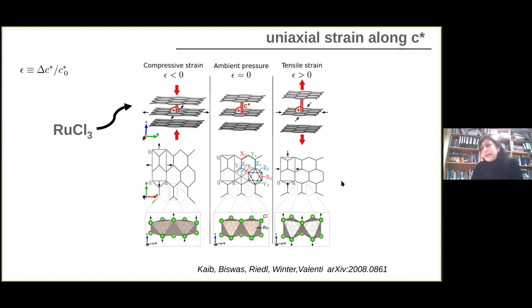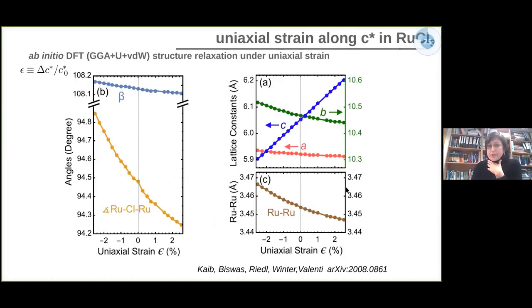So you can very nicely see these different cases by doing ab initio calculations, and you can see precisely what I was describing to you now in terms of these graphics, where I show how the angles, ruthenium chlorine ruthenium, change when we press. This would be the uniaxial strain, or we go away. This would be the positive uniaxial strain, and the same is about the distance of ruthenium and the lattice constants.